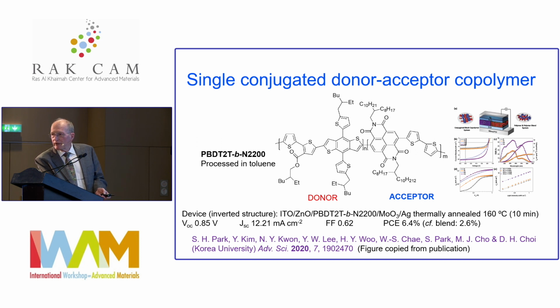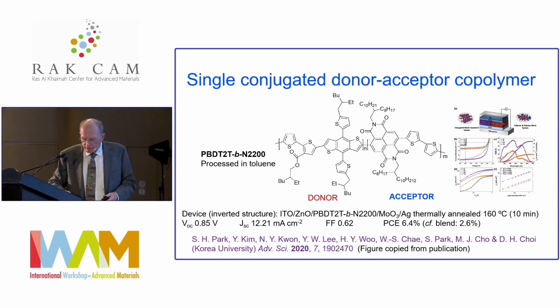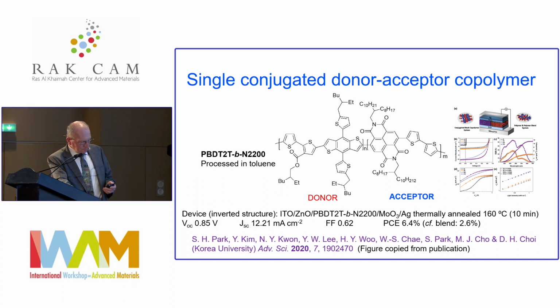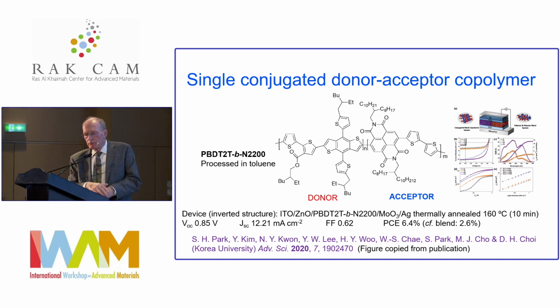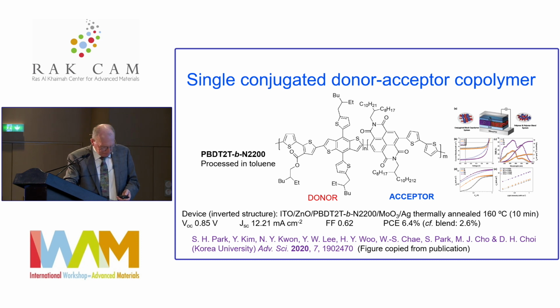But you see, it's the fill factor that's pulling it down more than anything else, although these could both go up a bit, because we saw, I think, 20 milliamps per centimeter squared in some of the best devices earlier. So that's where we are with the blended materials. And by the way, the morphology of this material, left and right, is represented by the blue and red color-coded, showing that the polymer self-assembles with all the acceptors stacking up on one side and the donors on the other.